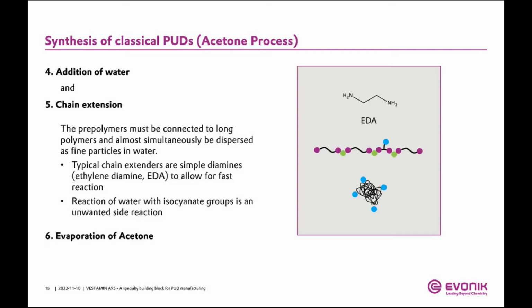So and then of course, this is an optional step. Some people do it without, some people do it with. So if you want to have a pure waterborne system, which has no VOCs, you have to make sure that you can now get rid of the acetone. The PUD technically also works without doing that, but nowadays we want to have pure waterborne systems. So that means we evaporate the acetone. Here we apply usually just a limited amount of heat, moderate temperatures. This is good for the stability of your particles, that you do not heat it up too much. And then you apply vacuum to just evaporate the acetone. And that is the reason why we chose the acetone in the first place, because it is relatively easy to remove via distillation or via evaporation.